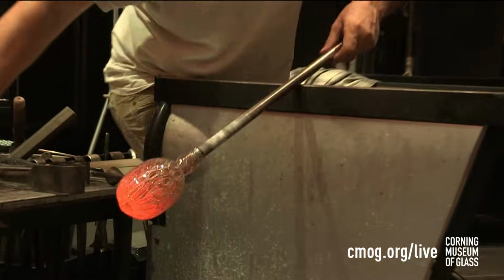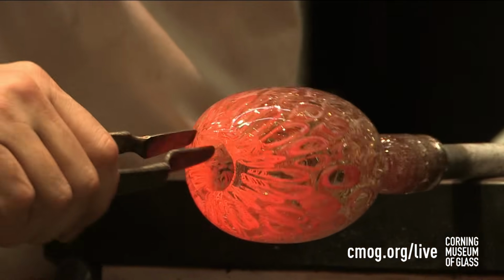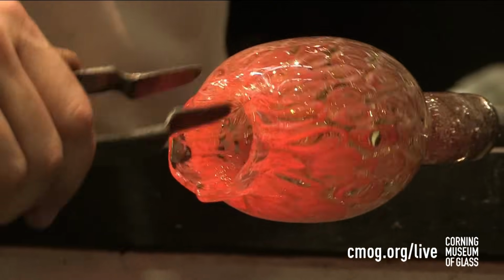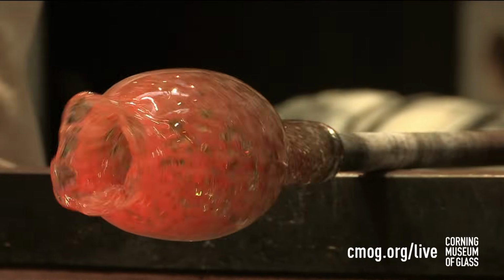But the important part is the tap on the pipe. That sends a vibration down the iron that will break the glass at that weak spot that we just created. Also, the jack line, which is the constriction that was created. That constriction tells the crack where to travel, so we guide the crack. Now, the difference between knowing how to break glass and breaking it evenly is experience. You can create a jack line, you can cool the glass down with a drop of water, but if you tap that pipe as hard as you can, you're still going to shatter the glass because it's still at a very fragile state. So you'll see this happen throughout the whole process when we transfer the piece from pipe to pipe. We will take every precaution during the punty transfer to control that break.